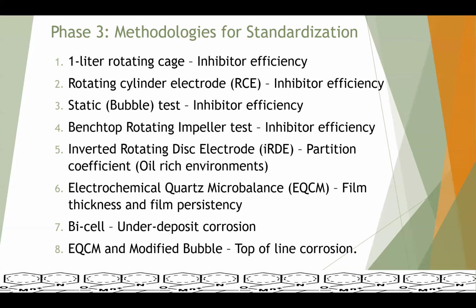Even though we recognize under-deposit corrosion to be an important factor, we do not have a standardized procedure to evaluate the efficiency of corrosion inhibitor to control under-deposit corrosion, for which we identified the Bi-cell. We'll be developing and standardizing it.